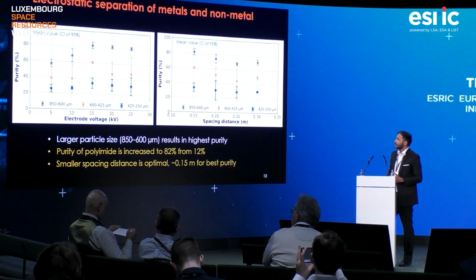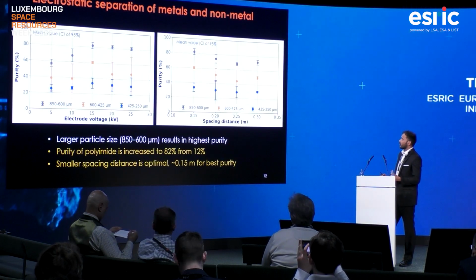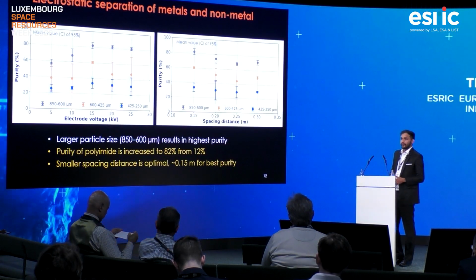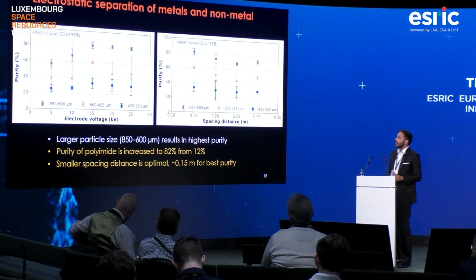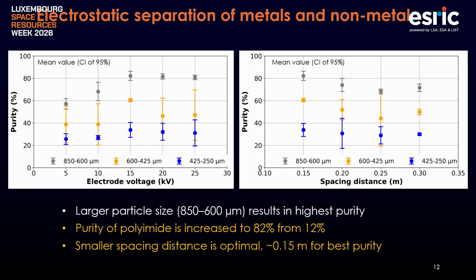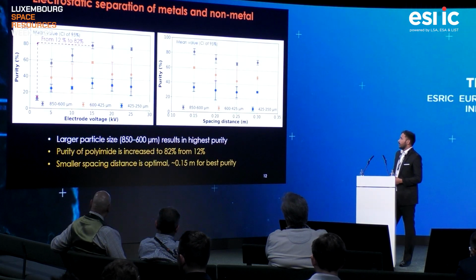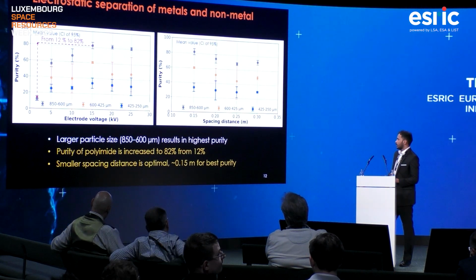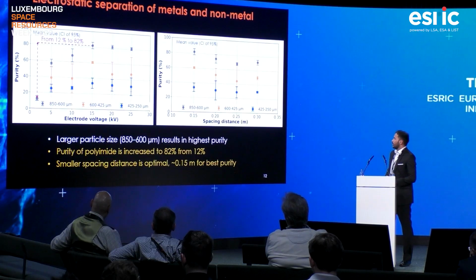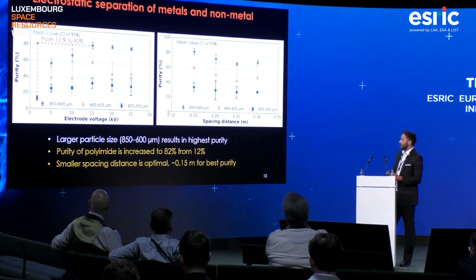We further analyzed the performance of the electrostatic separation with varying electrode voltage. In the separation process there are many different parameters, but we wanted to see how the performance varies with the electrode voltage, varying from 5 kilovolts to 30 kilovolts. What we've seen is that larger particles show the highest purity, so particle size is also really critical for this kind of separation. The second thing we achieved is an impressively high purity of the polyimide with these electrostatic separations, from 12% to 82%, which is quite good. In terms of spacing distance, we varied it from 0.15 meter to 0.30 meter, and we found that a smaller spacing distance gives the highest purity.